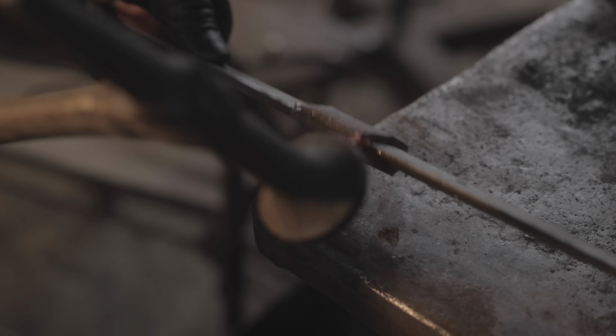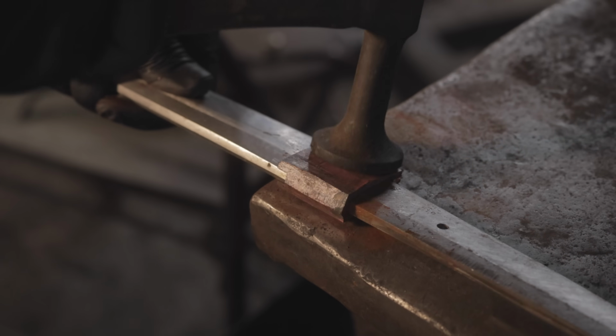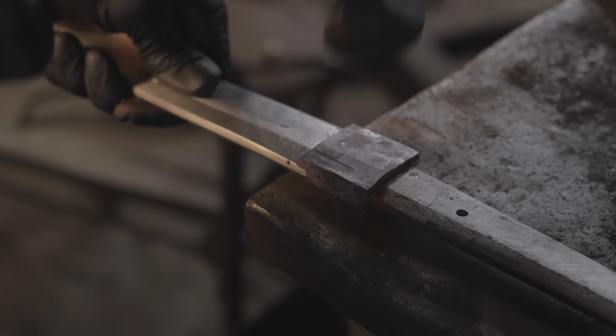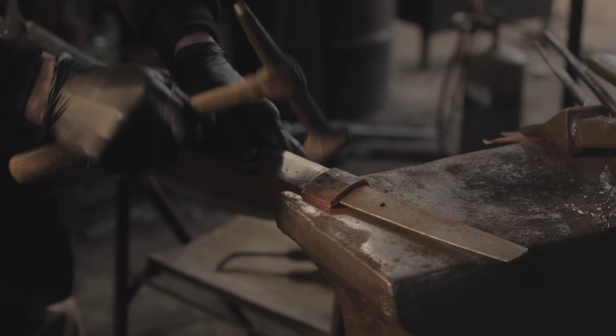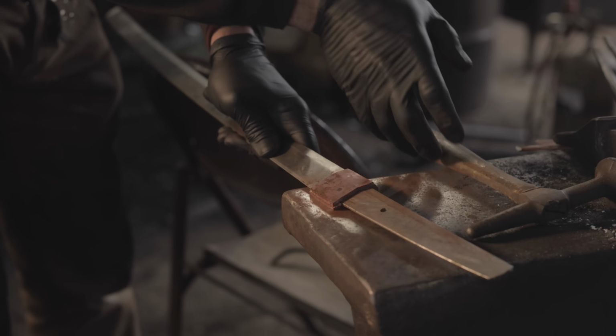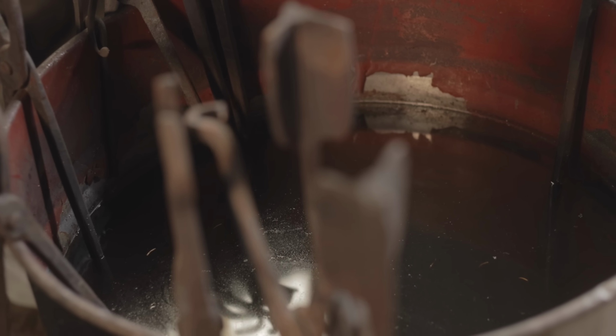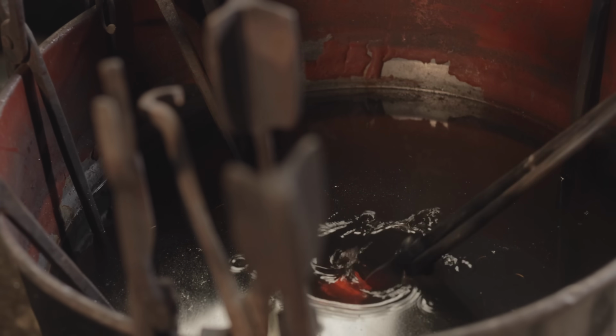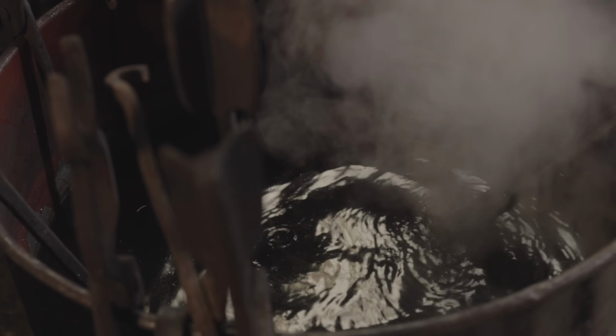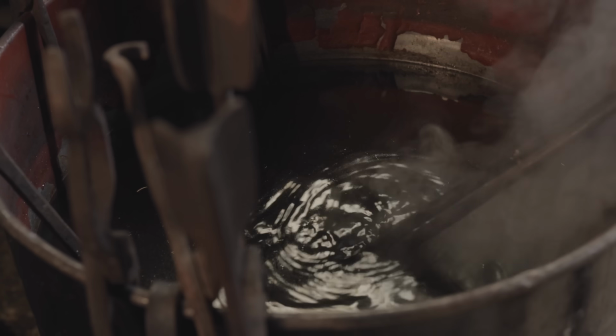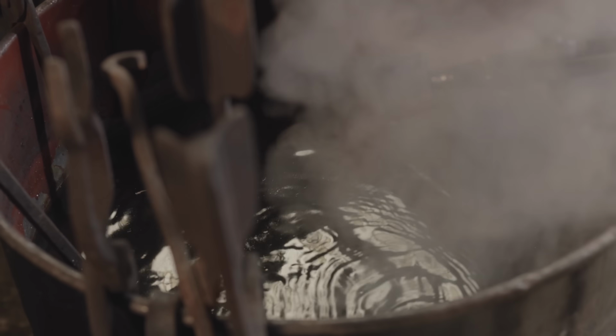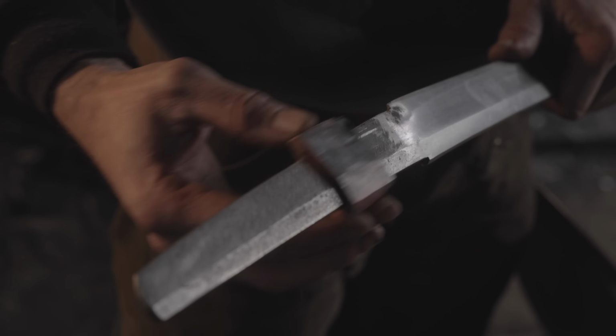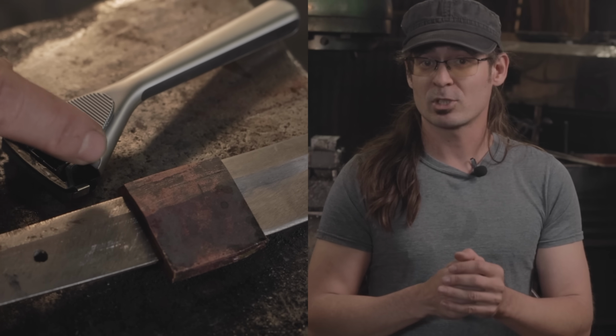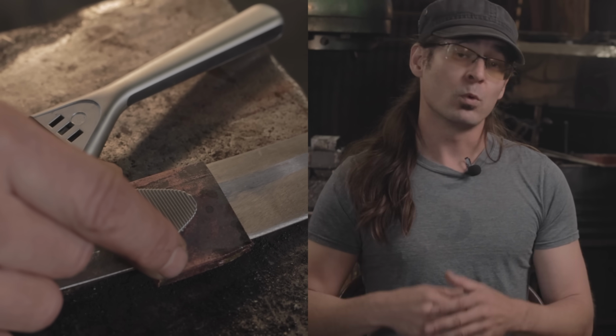So once again, even in circumstantial evidence, there's enough there to conclude that some Wootz ended up in the hands of some Japanese smiths, and it was fashionable, almost a challenge, to make a good sword out of this new type of material, even if the smith is bad-mouthing it. And that's not uncommon because I bad-mouth Wootz all the time when I'm working on it, sometimes even in front of the camera. Wootz is a difficult material to work with and is very idiosyncratic in the way you process it.